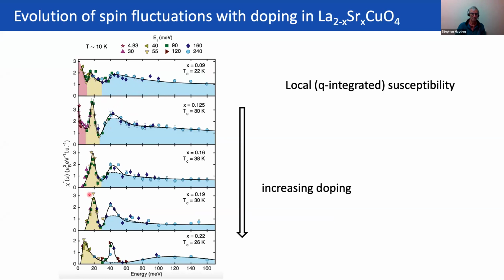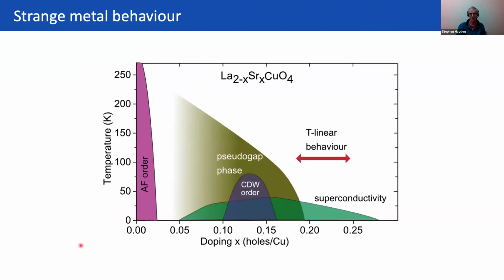You can see these are all measured in the superconducting state. So actually it pushes the spectral weight up above the gap, and you see a so-called resonance. But you can see it occurs across here. So this is the old data we had over a much bigger energy range. We're going to now look at this thing here in detail. This plot here is actually in the superconducting state, so it's quite strongly peaked. Okay, so the sample I'm going to talk about is here.